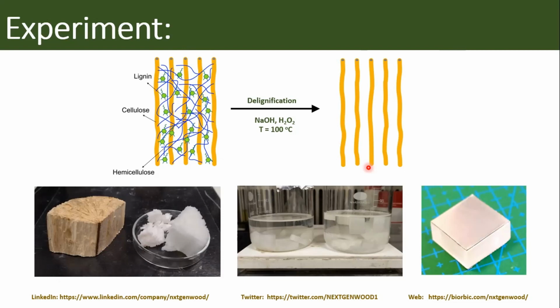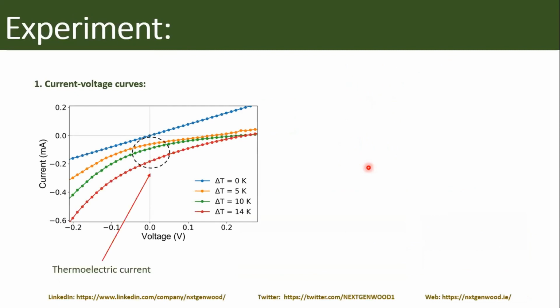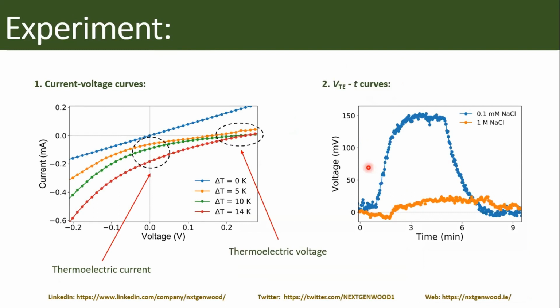Yeah, I'm from ISD in Japan. So can you show me your current voltage scan again? I don't work in this system, but I feel that if you scan from larger than the open circuit voltage and the short circuit current range, actually you are charging your device. So that could make the curve change. I guess, I don't know, because there's no electron transfer between your ions and the electrode. So I feel that for this system, probably it's better to determine the open circuit voltage first and scan from the open circuit voltage to the short circuit current, but don't overlap the range. That is what I feel.